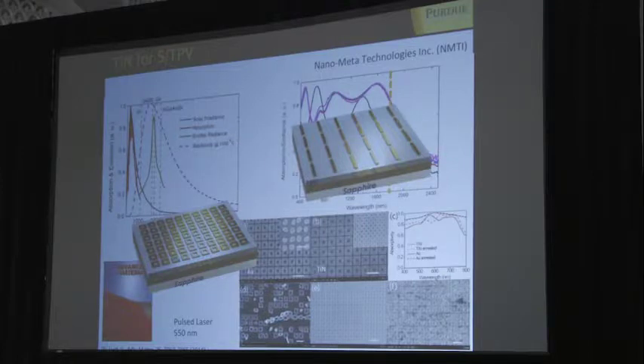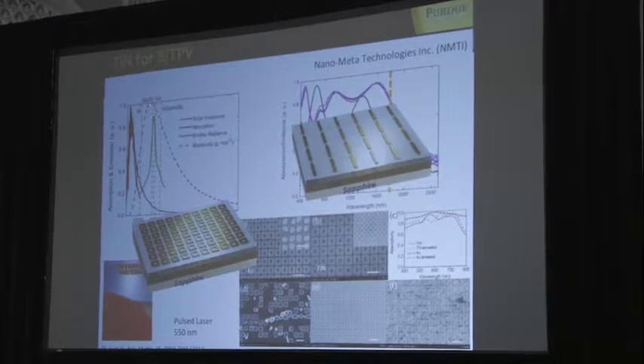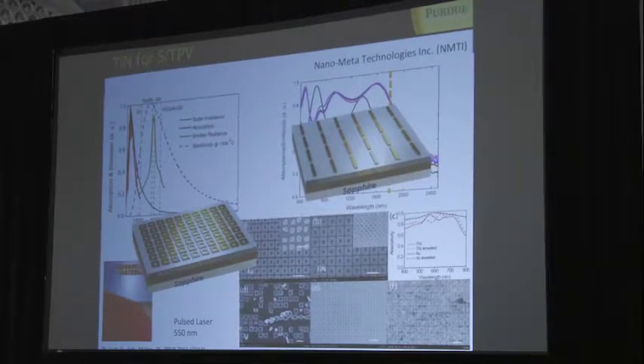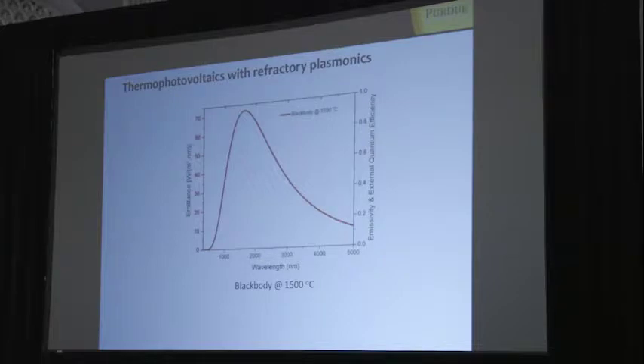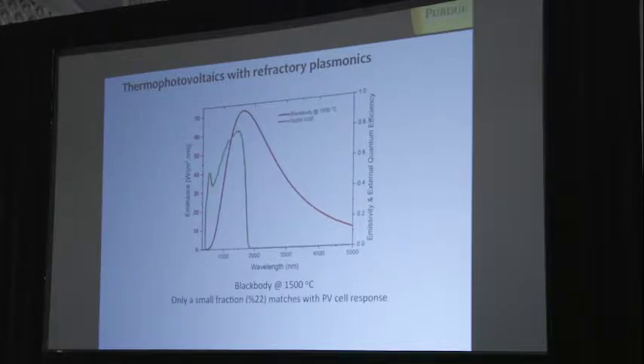So here you could see that it is designed so that it emits the wavelength which matches very well the band gap of gallium antimonide. And if you look at what kind of efficiency you should expect in this case, this is a Planck's radiation of a black body at 1500 Celsius. This is efficiency of conversion for these gallium antimonide photovoltaic cells, and you see that only 22% matches with a photovoltaic cell, so you lose lots of energy in this case.